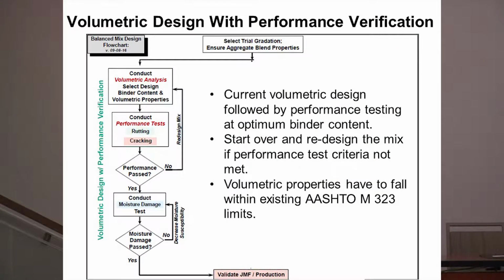This particular one is for the volumetric design with the performance testing. In this approach, you would do the volumetric design as we do it now in AASHTO M323 and AASHTO R35, and you will come up with an optimum binder content. Then you would perform the performance testing for cracking and rutting resistance at that optimum binder content. If it does not pass the criteria that are given, then you redesign the mix and start over.